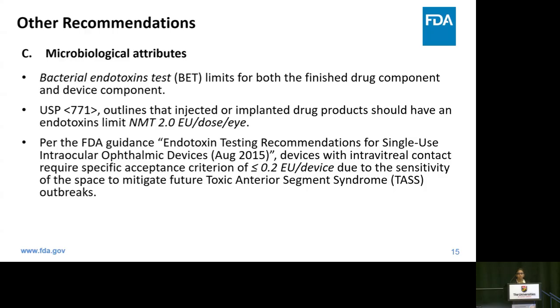So now next is microbiological attributes. Since this is a complex combination product, in this particular case the bacterial endotoxin test should be evaluated separately for the drug product as well as for the device. For the drug product, the applicant can refer to USP 771, which also outlines the specification limit of not more than 2 EU per dose per eye. Regarding the device, you can also follow the guidance on endotoxin test and recommendation for single-use intraocular ophthalmic devices, in which the recommended limit or acceptance criterion is not more than 0.2 EU per device. And until this endotoxin evaluation has been performed, those applicators are not acceptable for use for intravitreal injections.